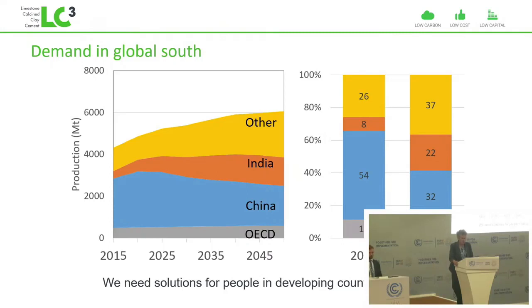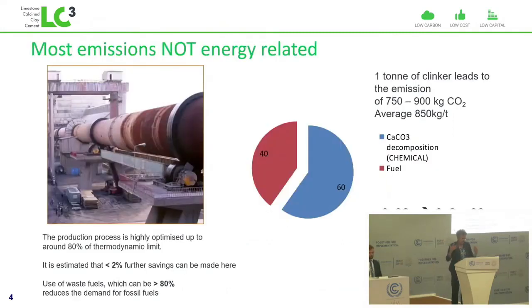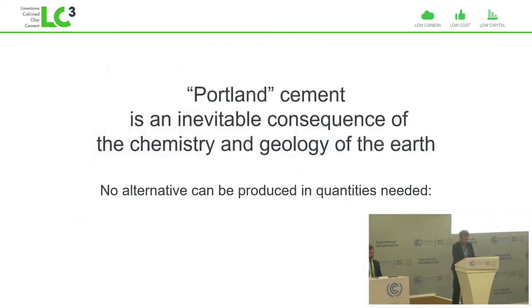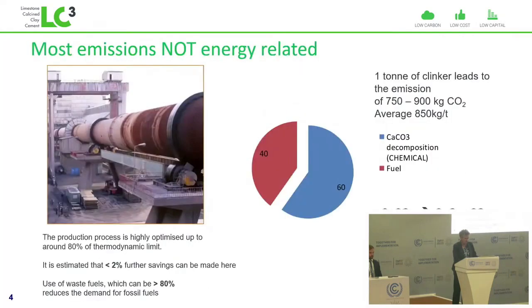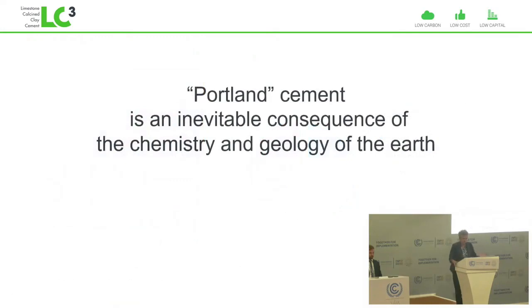Well, we are limited by what we have available. So unfortunately, most of the emissions which are coming from cement are due to this breakdown of limestone, calcium carbonate, which breaks down to calcium oxide and CO2. So people say, well, can't we produce something different? But the long and short of it is that Portland cement is actually an inevitable consequence of the chemistry and geology of the earth. And there's no material which can substitute it in the quantities we need.